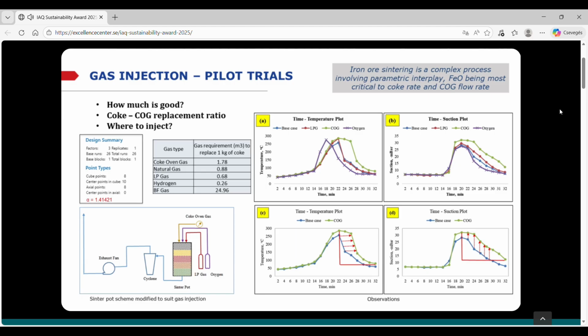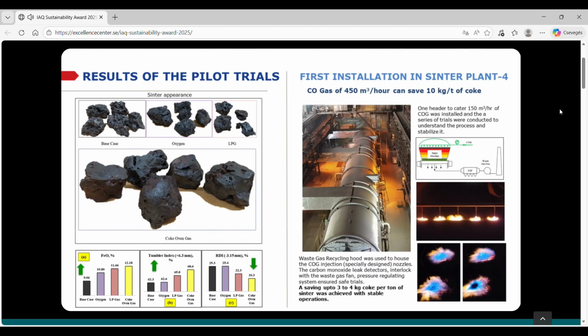Oxygen, which can improve the combustion efficiency of coke, and liquefied petroleum gas, LPG, as an alternate gaseous fuel were injected to see their effects. The coke oven gas has about 57% hydrogen, a carbon neutral source of heat and reductant of the iron ore. When injected, COG outperformed LPG. Hydrogen in the COG enhanced FeO formation. Superior mineralogical phase assemblages were noticed, which resulted in enhanced properties of the sinter. The voice of the process indicated improved thermal regime and mineralogy.